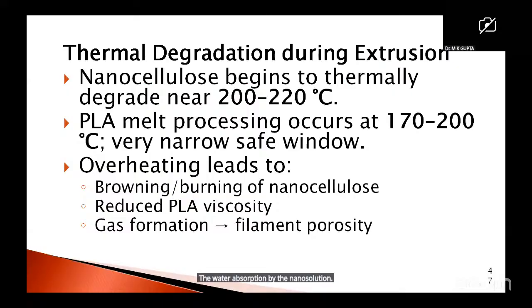Thermal degradation. Nanocellulose thermally degrades near 200 degrees centigrade, and PLA melt processing occurs at 170 to 200 degrees centigrade. So as you can see, there is a very narrow safe window.